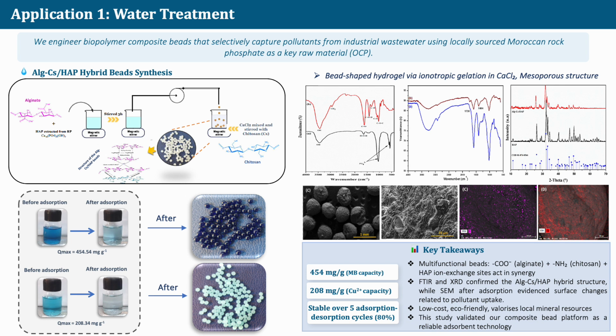So our first application focused on water treatment using alginate-chitosan hydroxyapatite hybrid beads. These beads were prepared by ionotropic gelation in calcium chloride using hydroxyapatite derived from Moroccan natural rock phosphate as a local mineral resource. The formation of the hybrid structure was confirmed by characterization. FTIR analysis highlighted the presence of the main functional groups from alginate, chitosan, and hydroxyapatite, while XRD confirmed the crystalline contribution of hydroxyapatite within the biopolymer matrix.